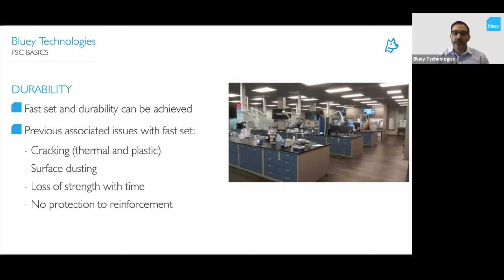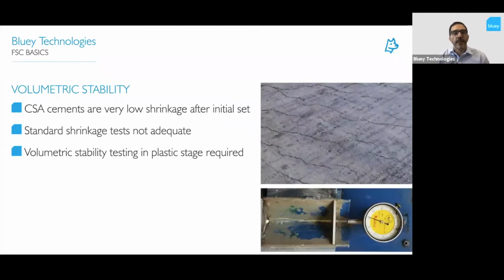People would see that you would get cracking, thermal and plastic, you'd get surface dusting, loss of strength over time, and they wouldn't provide any protection to the reinforcement because either they had chloride-based accelerators which would attack the reinforcement, or they wouldn't be alkaline, so they wouldn't provide that alkaline environment to passivate the steel. So these were all issues that were associated previously, going back maybe even 10 or 20 years. Now you don't see that.